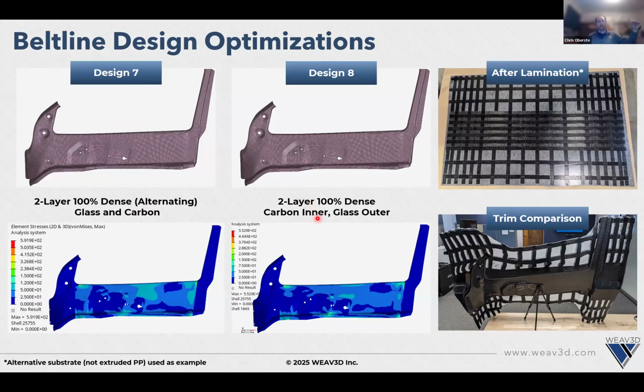But even if you look at these 2 different designs, alternating stripes versus stacked stripes, so this is carbon fiber on the inside, then a layer of glass on the outside, the stress distributions on these 2 parts are very different. And this is because where you put the reinforcement in these metamaterials is as important as what reinforcement you put in them.